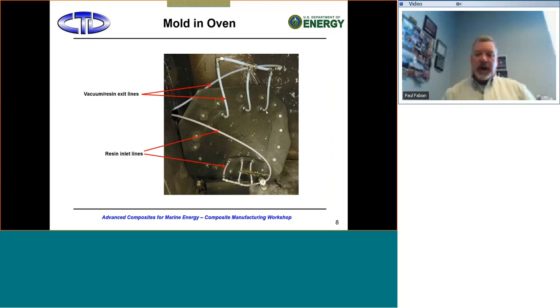And you can see this is a composite tool. This was a prototype, so we weren't looking at long-term production here, so we went with a cheaper option and fabricated the mold out of a carbon fiber composite itself. And you can see the outline of the blade here, and you can see where the resin inlets are below the blade, the resin exit ports are above the blade inside there. And of course, in this case, the resin we're using is an elevated temperature processing resin. So this is all done inside of an oven that you can heat up. In this case, we were impregnating at 80°C.